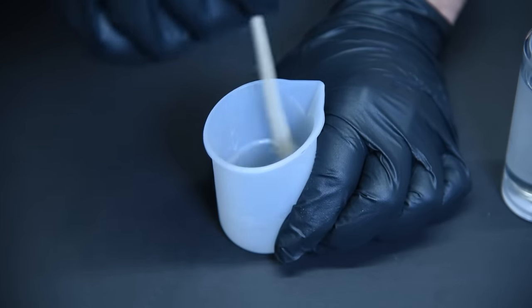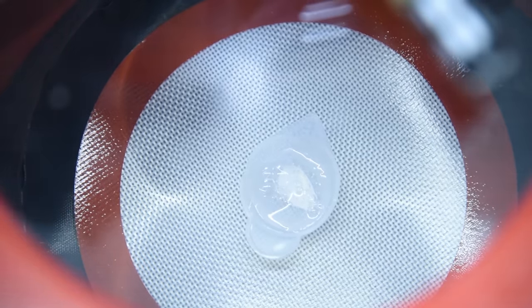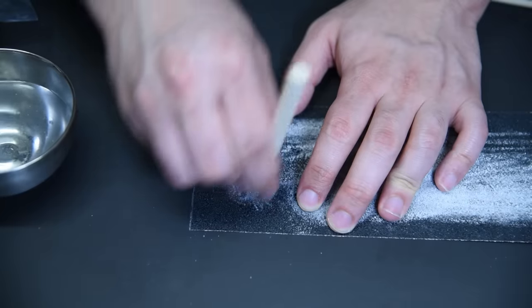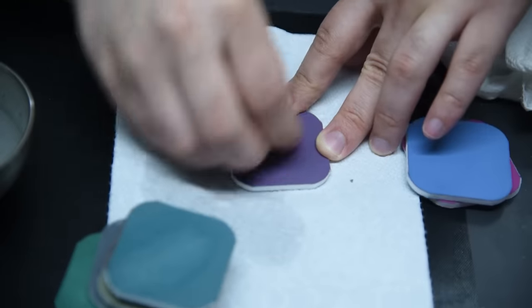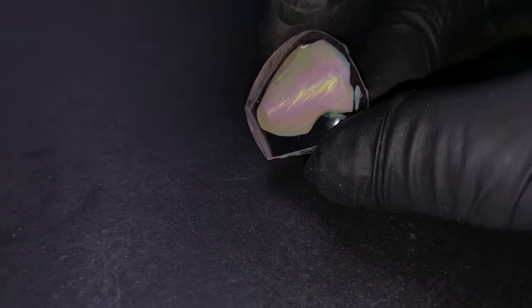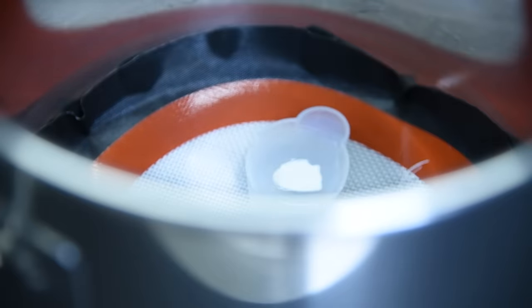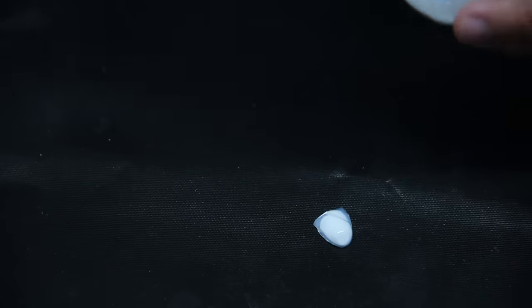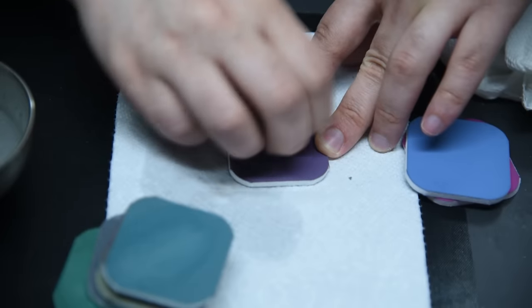For the art resin, I mixed up about 20 milliliters of resin and degassed it thoroughly in my vacuum chamber, before pouring it over a sample of opal which I'd put in a little silicone mold. This was then again vacuumed to try and force the resin into the opal, but evidently that doesn't actually work very well. After that, I sanded it with regular sandpaper and polished it with micromesh polishing pads. For the UV resin samples, I also used the vacuum chamber to force the resin in, and this time it's clear that it actually penetrates into the opal structure. Before curing, I fished the pieces out so there isn't a ton of excess resin to remove, then cured them under a bright UV light for 20 minutes, before sanding and polishing just like before.